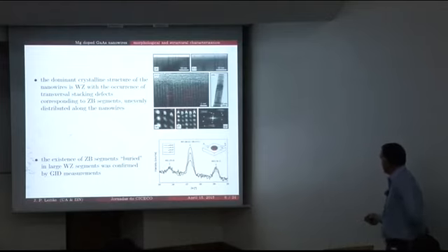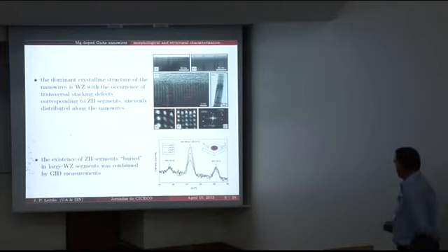We concentrated mainly on this range of angles here, in which you can see three different reflection peaks. These peaks here, the one on the left and the one on the right, have origin just in the reflections from the wurtzite crystalline phase, and the peak here in the middle has two contributions, one from wurtzite and another one from zinc-blende.